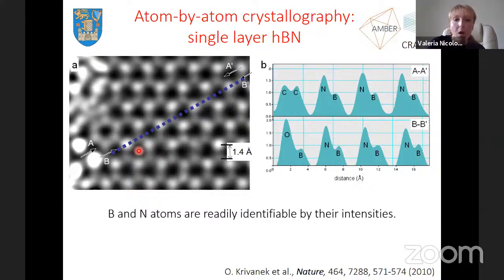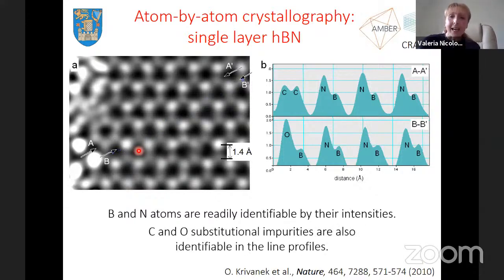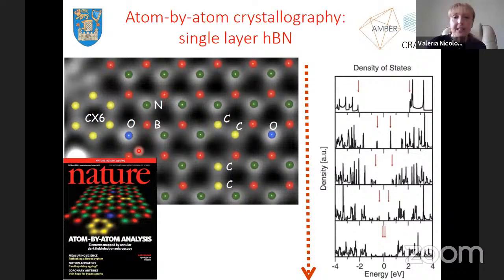So all we learned was that liquid phase exfoliation created these structures that were really not perfect. Once again, not perfect, and the electronic behavior of this material was indeed changing with these inclusions. Well, we learned that, for example, carbon was always replacing pairs of boron and nitrogen, never one atom only, always pairs, and that oxygen always replaced nitrogen.